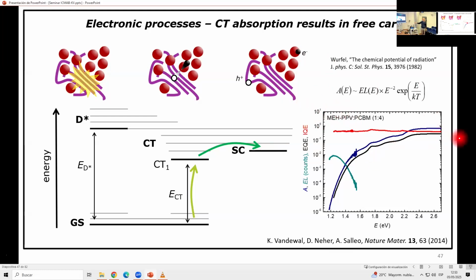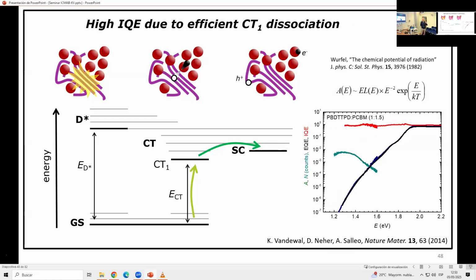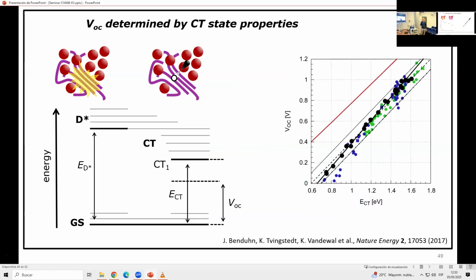And if it's a good solar cell material, the splitting efficiency is 99.9%. And for a bad one, it's then 70 or 50%. This is a better material. It's the same. So you see that the exciton, or the CT state, splits as efficiently as wherever you excite. So it's not really a trap. This interfacial state helps to split charges, but it's also the place where the charges meet. That's how you should see it.